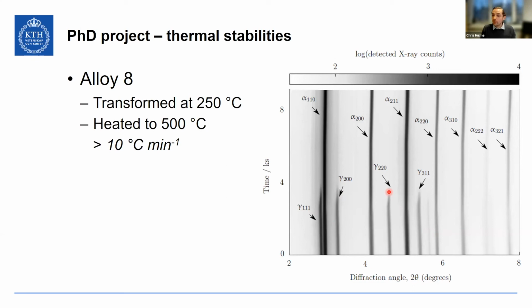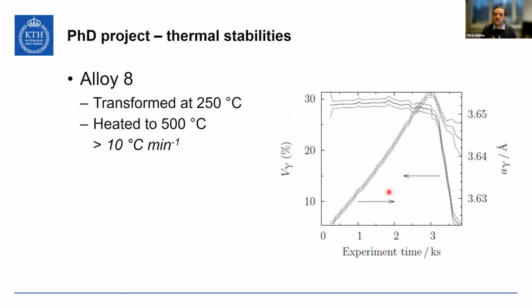And you can see that very clearly if you do the Rietveld refinement and look at the austenite volume fraction. Over time, in the early stage it's quite stable at sort of 28% plus or minus 2% or thereabouts. And then the lattice parameter increases pretty linearly until it reaches a maximum. And after the lattice parameter begins to reduce, the austenite basically disappears almost entirely from the system, leaving a very small amount of residual austenite afterwards.